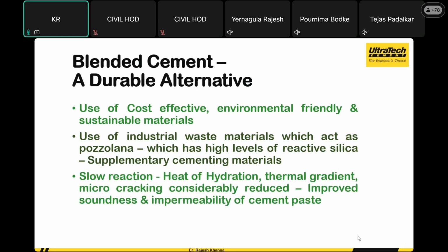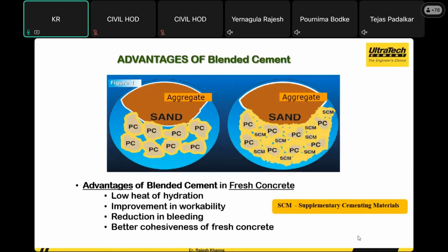Now when we use these supplementary materials or blended additives, they have a slow reaction, where we see the heat of hydration is very low, micro cracking is considerably reduced, and there is improved soundness and impermeability of cement paste. That's how we see sustainable or durable options keep coming up when we use blended concretes or blended cements in our construction. We could see better reduction in bleeding. The mix is going to look like kozu, like our curd rice that we see. So much improvement in workabilities. That's how supplementary cementitious materials keep helping us.